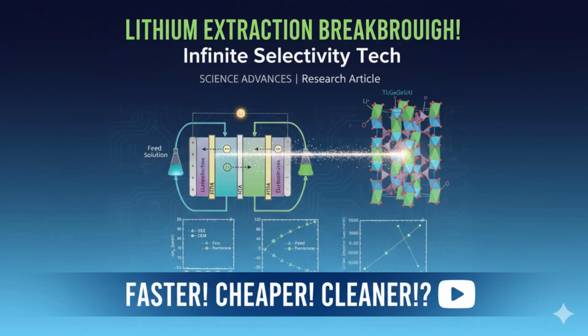And the claim, as the title suggests, is pretty extraordinary. They report, and I'm quoting here, unparalleled performance. Specifically, lithium-ion selectivity values so high they are immeasurable by even the part per billion detection limit of mass spectrometry. I mean, think about that. Immeasurable selectivity. So what does that practically mean? When they say immeasurable, they literally couldn't find any other ions getting through. That's exactly what they're saying. They set up their system, put a solution with lithium, sodium, magnesium, potassium, etc.